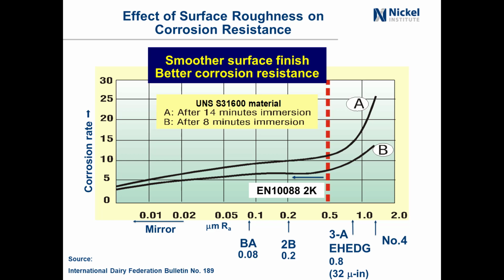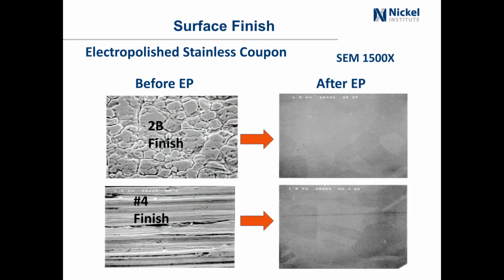And the 3A and EHEDG surface finish values are here at 32 microinches or 0.8 micrometers. So once you get beyond that, the corrosion rate on your stainless steel would increase. This is what a 2B finish would look like, magnified, and this is a number 4 that would be polished from a 2B, and then what the surface could look like after electropolishing.